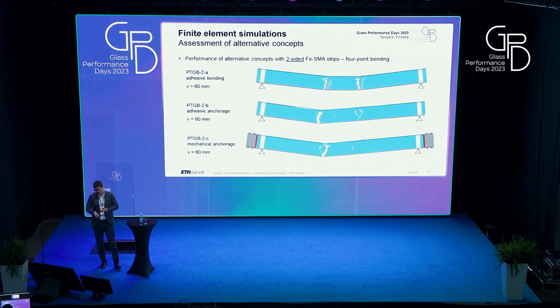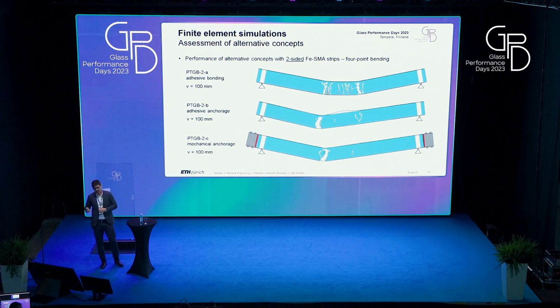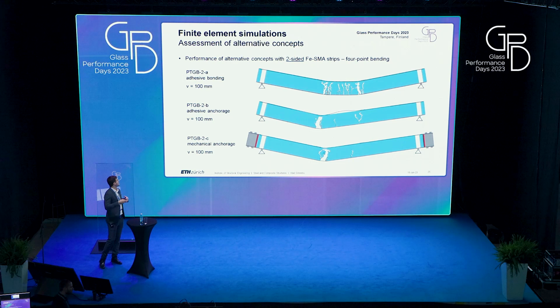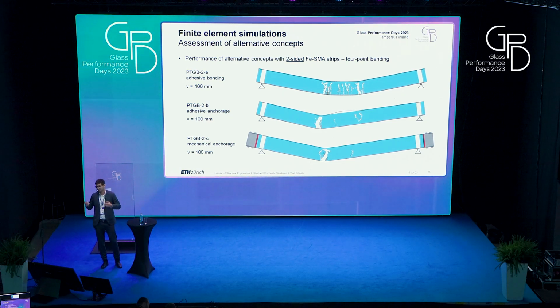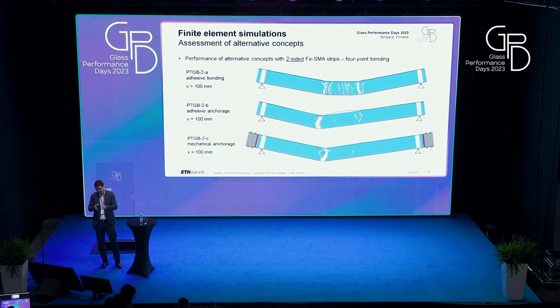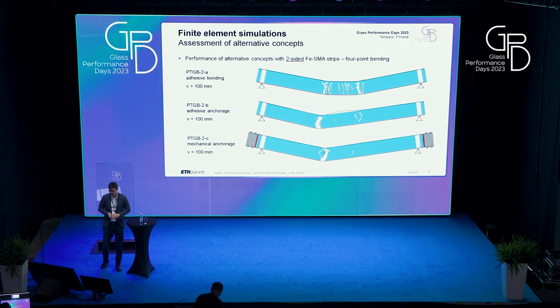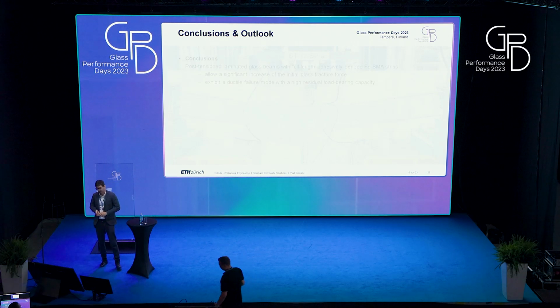And then when we load it further, for the one with bonding along the whole length, we have several cracks distributed. For the one where we don't have adhesive in the middle part, the main crack will just get larger and larger. I'm now coming to the conclusions.